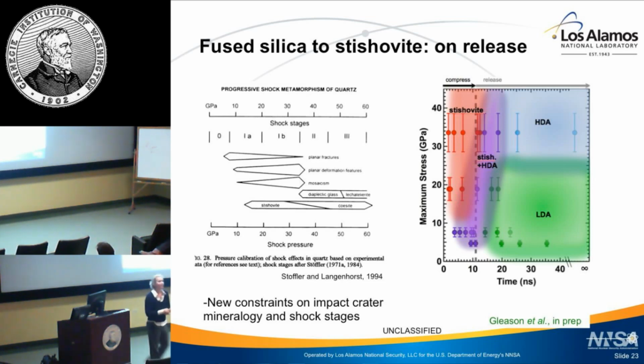So this is really exciting because I can go back to the work of, say, Stöffler, Langenhorst, DeCarli, folks who've looked at recovered material, tried to establish from a shock metamorphism perspective a pressure mineralogy scale for impact sites. And we can now add this new component of time and think about what effect that has, and maybe recast some of these shock stages in the context of when this diaplectic glass is forming, how stable it is as a function of peak pressure achieved. So this is very exciting on providing maybe some new constraints for some of these different shock stages.